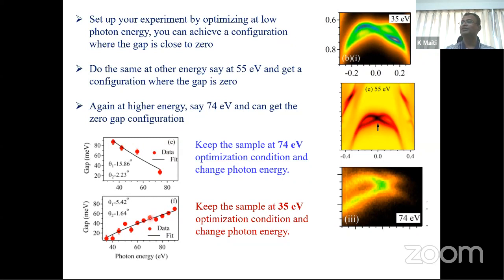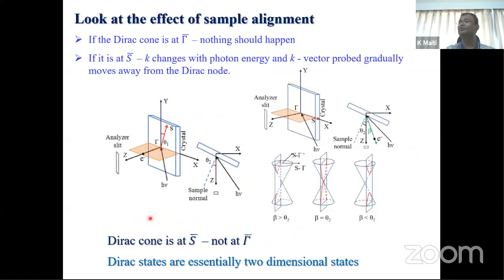So this shows that this finding of a gap at the Dirac point is an experimental artifact, not really a property of the material. Okay? So what could happen? If you are looking at the gamma point, of course, it's a 0, 0 point. So even if you change photon energy, which changes your kz vector, you don't really change the 0, 0 point of your k. So that way you should be having the Dirac node satisfied at all the photon energies, but that's not happening in the experiment.